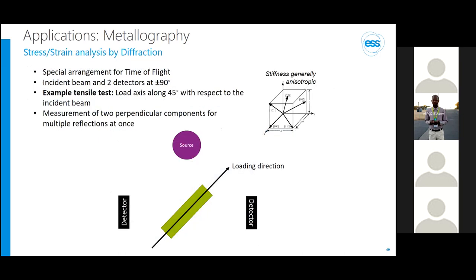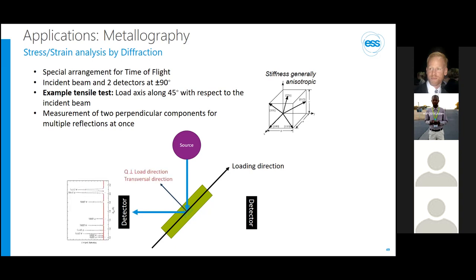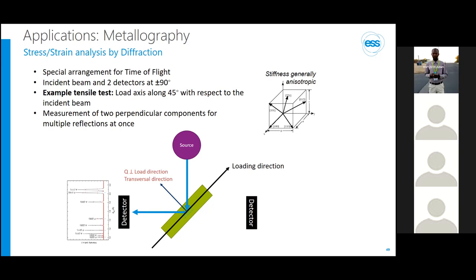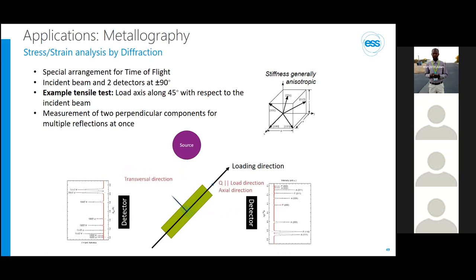At the ESS and also at other engineering diffractometers, primarily at spallation sources, there are setups like this with diffraction detectors at plus minus 90 degrees. If we perform a tensile test, this green sample you can envision being a tensile sample, and if we pull on it, then with diffraction detector one we obtain the Poisson strain. The other detector measures the strain component along the axial direction. So you're getting two strain directions simultaneously in one measurement by using these two detectors.